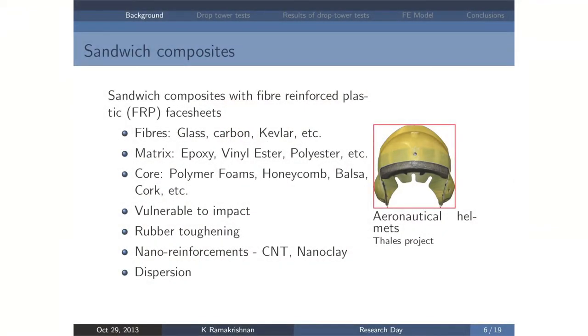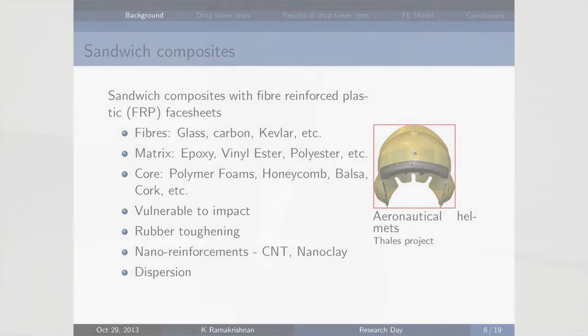Traditionally, sandwich materials have used conventional metals like aluminum for the face sheet or skin. But new sandwiches with fiber-reinforced plastics have also been used in modern times. In the fiber-reinforced face sheets, the thin stiff skin is made of a fiber in a polymer matrix. The fiber can be glass, carbon, or Kevlar. The matrix is a polymer resin like epoxy. The core of the sandwich material, because we require a lightweight low-density material, can be polymer foams, honeycombs, wood, etc.